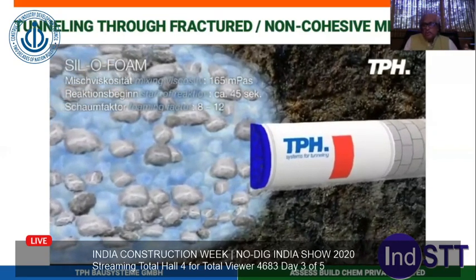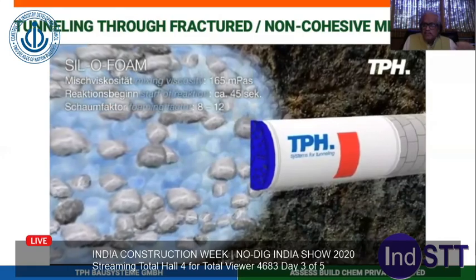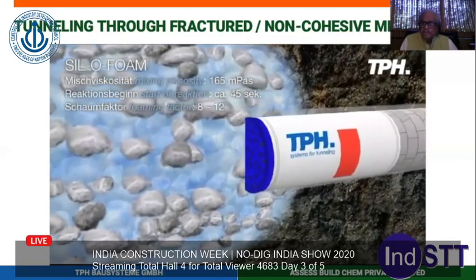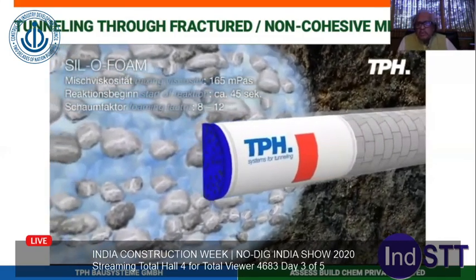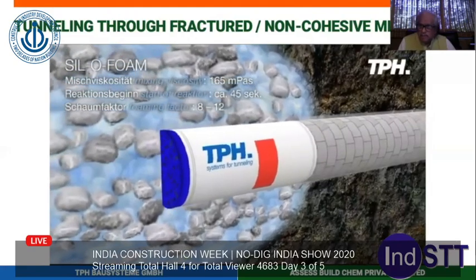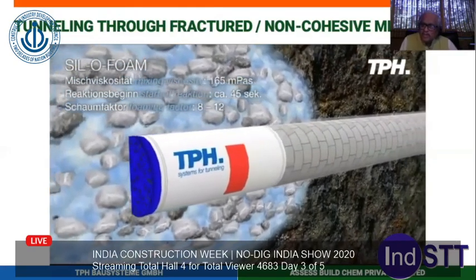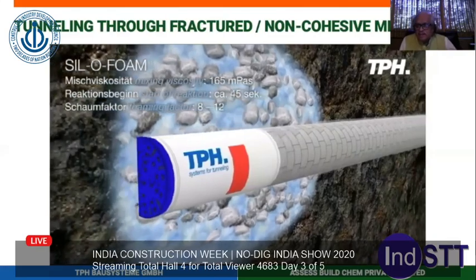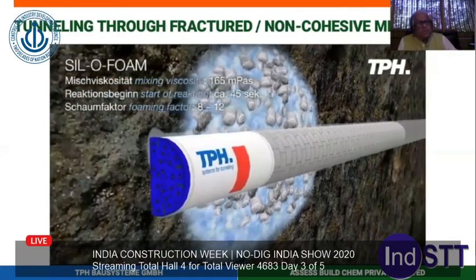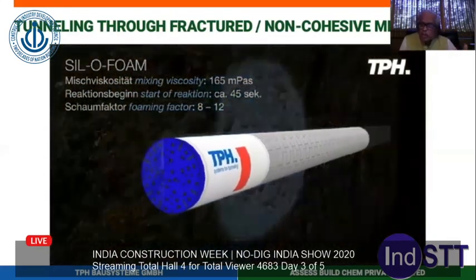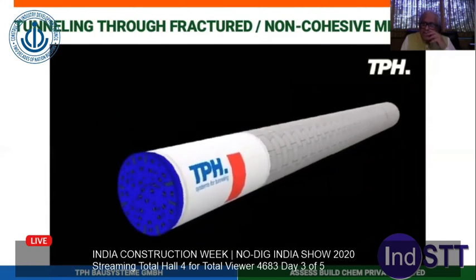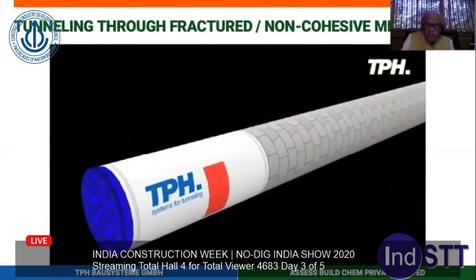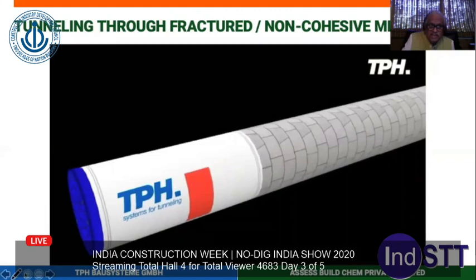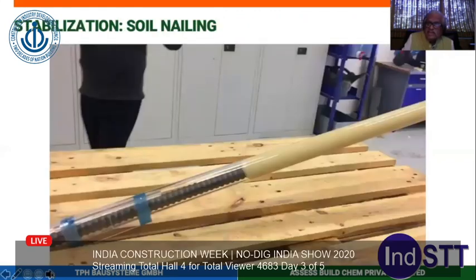See, one thing you have to remember, you'll see some certificates which will tell you my foaming is 1 is to 15 and my compressive strength is 15 Newton. This is not possible. Because on one foaming factor they give, the tests are done with only 1 is to 1 or 1 is to 3 foaming factors. So you can't have both things. As the foaming increases, the compressive strength decreases.